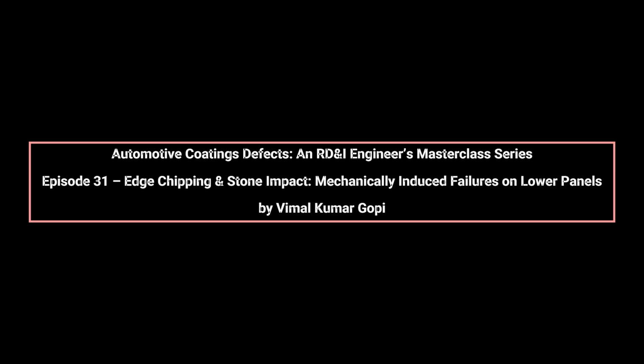Cure and crosslink density significantly influence impact resistance. High crosslink density improves chemical and MAR resistance, but reduces elongation, rendering the coating brittle under point impacts. Low crosslink density coatings are more flexible, but can deform permanently, trapping debris and reducing gloss. OEM formulations are optimized to balance hardness, elongation, and stress relief to resist both stone impact and cumulative mechanical fatigue.